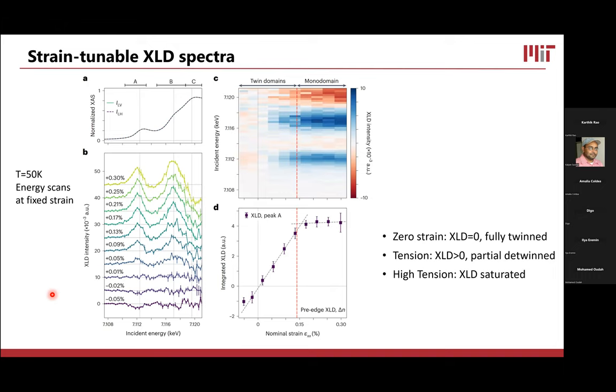Okay, so now we can consider what happens to the XLD as we move across a large strain range, from a little bit of compression, because it's hard to compress the titanium bridge, to a very large value of tension, because it's easy to apply tension to the bridge. So then we get line cuts that look like this. Each one of these is the difference of the two linear polarizations of the X-rays across this large energy range. And again, we have the A, B, and C features.